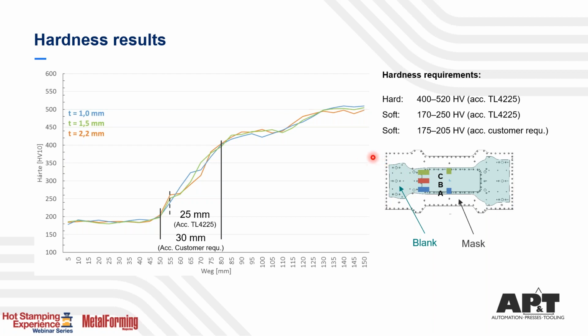for different sheet thicknesses. And what you see here, if we have, in this case, 205 Vickers up to 400 Vickers, we get a transition zone between 25 and 30 millimeters in length.